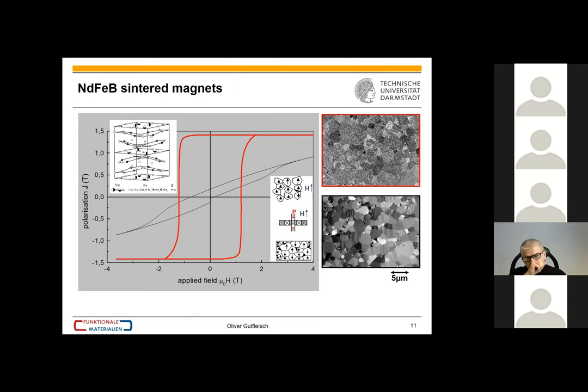So here now, just the basics, that is a very good permanent magnet. As you know, that is state of the art. We see the easy and hard directions of magnetization. And the crossover of the easy magnetization and the hard direction of magnetization somewhere down here, that is the anisotropy field of this compound. On the mesoscopic scale, we see by Kerr microscopy the qualitative reflection of texture, of stripe-line domains, and this second pattern here with the c-axis perpendicular to the imaging plane.